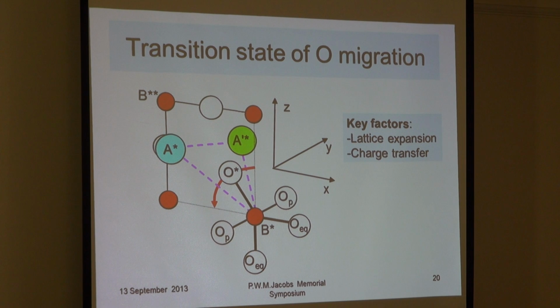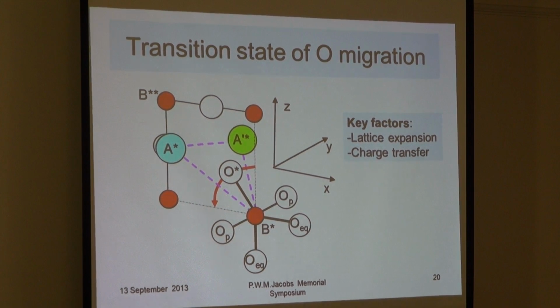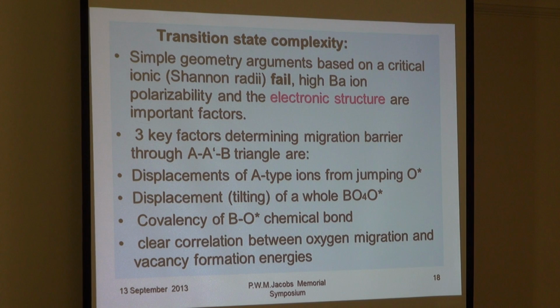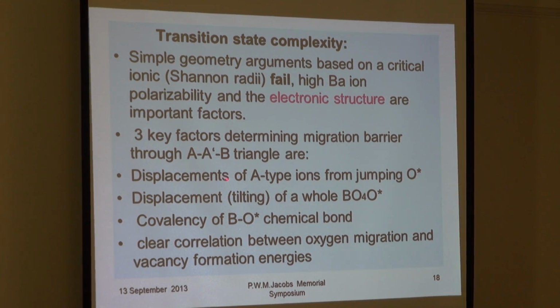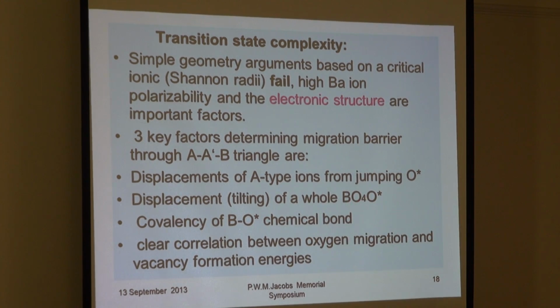Second, very important, what we found is that there is charge transfer between oxygen and the B-type cation. And in this material, in BSF, there is considerable charge transfer. So oxygen becomes smaller and it goes through more easily. And if you take, for instance, LSF, in this case there is almost no charge transfer and the energy becomes larger than in BSF. Second, the whole structure is also deformed during the migration, and there is a tilting of octahedra in this structure.